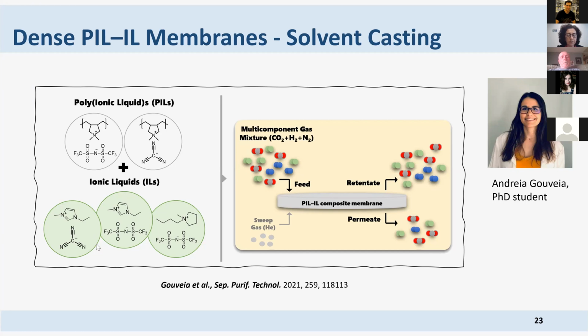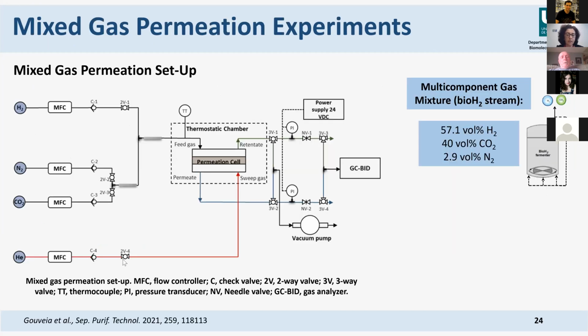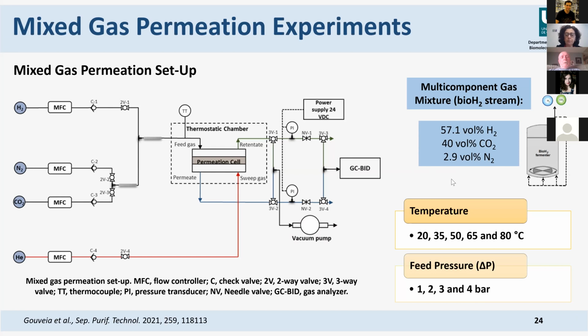So Andrea prepared PIL composite membranes, dense composite membranes. And the novelty here was to check how a mixture of gases would behave in comparison to pure gases. This work was done in collaboration with the University of Santander in Spain, with the group of Immaculada Ortiz and Daniel Gorri. So this is the typical composition of biohydrogen. And here we did our experiments at temperatures between 20 and 80 and feed pressure between 1 and 4 bar.